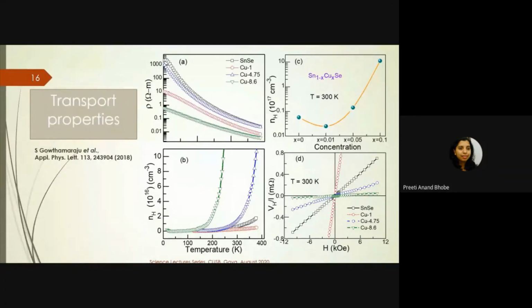If you also look at the charge carrier concentration from the Hall effect measurements, like shown in the lower right panel in the figure, then we see that the black curve is for SnSe. Compared to the black curve, initially when you put very little copper, suddenly the slope changes. It is showing a decrease in the carrier concentration. And that's just for 1%. Maybe it is because it generates some internal strains in the crystal unit cell. But as you increase the concentration higher, the slope of the curve changes, and it is coming, the blue and the green curves.